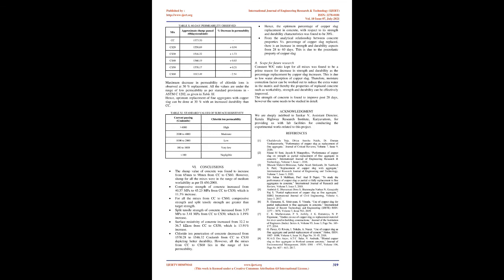This is due to low water absorption of copper slag. Therefore, a moisture correction factor can be worked out to reduce the extra water in the matrix, and thereby the properties of replaced concrete such as workability, strength, and durability can be effectively improved. The strength of concrete is found to improve post 28 days; however, the same needs to be studied in detail.